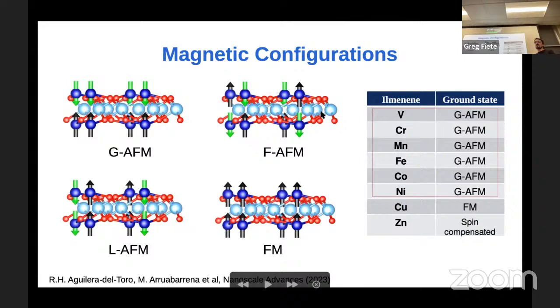As far as I know, they have not been made in thin film or two-dimensional form, which is the whole thing we were trying to do: setting the ground for future experiments. We are not completely sure, but if they have done it with iron, and we have cobalt also, which is interesting, there's probably a way to do the two-dimensional, and it's really interesting. So in this case we just have the experimental values for iron. But we see that most of them have this ground state, which is the one we observed in bulk cobalt.